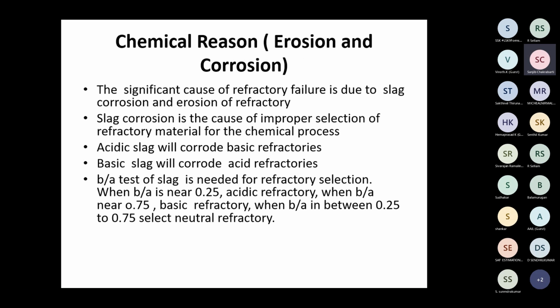The chemical cause of refractory failure: the significant cause of refractory failure is slag corrosion and erosion of the refractory. So these are the main causes, and the damage to the refractory is due to this. Out of all reasons, this is the biggest cause of refractory failure. Slag corrosion is caused by improper selection of refractory material for the chemical process.